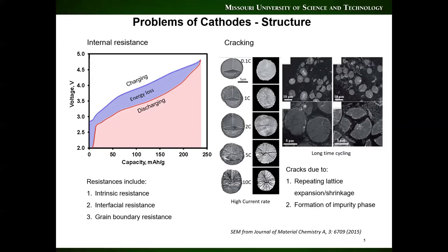And the cracking of the particles will aggravate the resistance growth during high current loading and long-time cycling, which is due to repeating expansion and shrinkage of the lattice structure during lithium intercalation and deintercalation, and also the formation and growth of impurity phase.